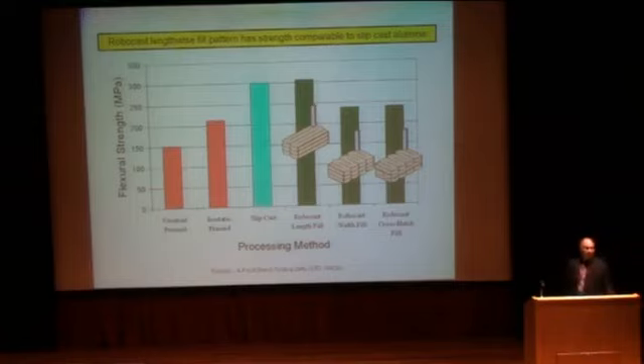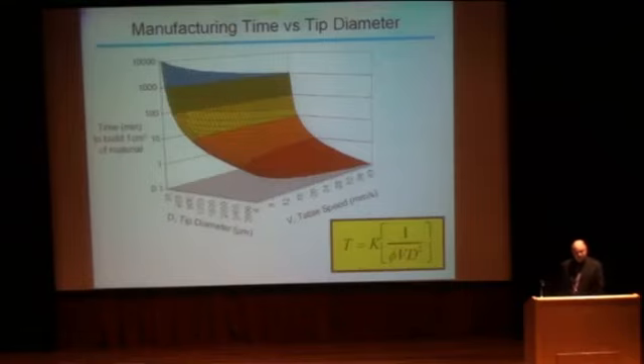So that's going to be a reality: if you want to use these for advanced ceramics and really push the limits of the material, this probably isn't going to be the best way to go. You're probably going to have to hot press and machine or something like that. The other thing to take into account is the build time, in this case the time to build 1 cubic centimeter of material. That needs to be on the order of a minute or preferably even less to be commercially relevant, economical enough so that you can compete with other ceramic processing techniques as a minimum.